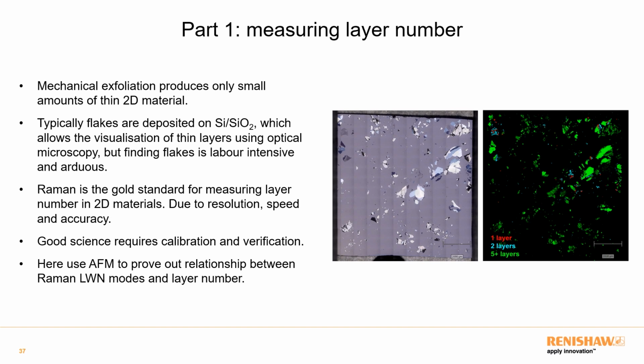So one of the challenges when dealing with 2D materials is the really common way of producing them is mechanical exfoliation. But unfortunately, this produces only very small amounts of material. And this can be challenging because you need to find the right layer thickness, and the exfoliation production method gives you a very large range of thicknesses. So the standard method is to take the flakes, deposit them on a silicon dioxide substrate, and this allows you to visualize the thin layers, so you get some optical contrast. However, it does mean that someone has to spend a lot of time staring down a microscope looking for the layers, and you still can't guarantee that you've produced them, so it can be like looking for a needle in a haystack.